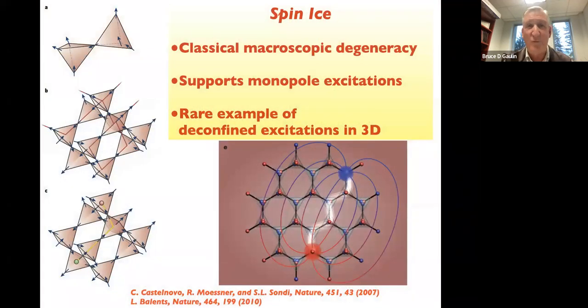And about 10 years went by with the introduction of this sort of problem, which is called the spin ice problem. And I should just mention it's called the spin ice problem because the degeneracy that you have associated with the 2 spins in, 2 spins out on a given tetrahedron, it's the same degeneracy that you have for proton disorder in certain phases of ice. This is the problem that Linus Pauling was working on, connected with ice in the 1930s, and that's why this problem as a whole is called spin ice, okay, which is a great branding exercise, by the way. People really like this term.